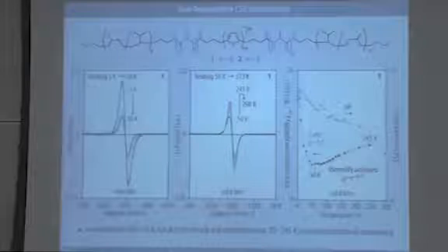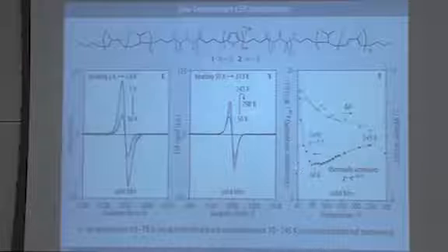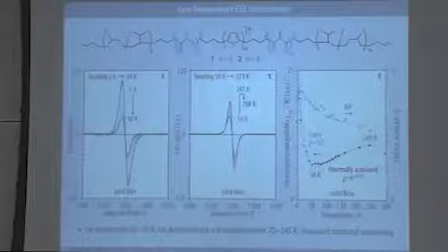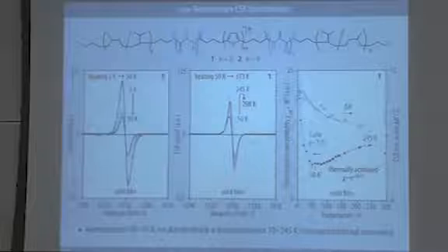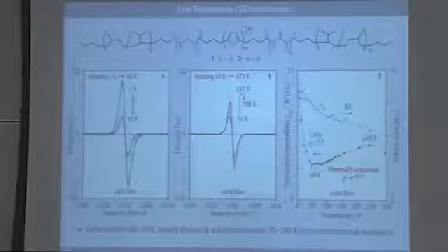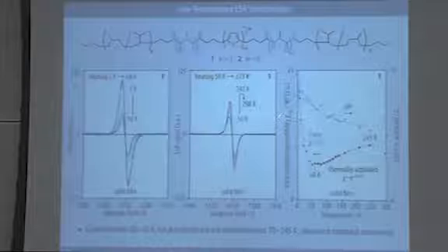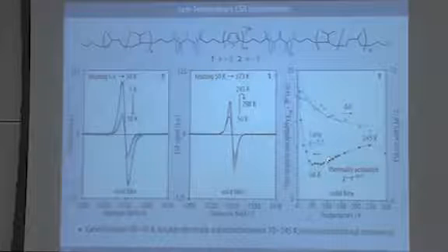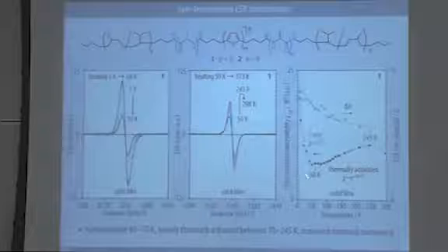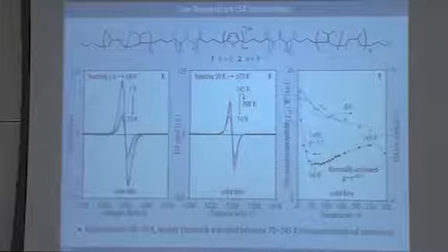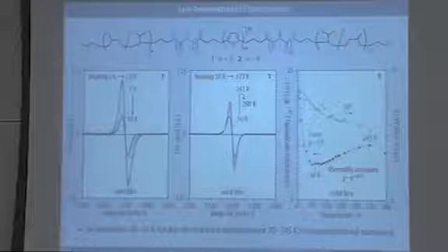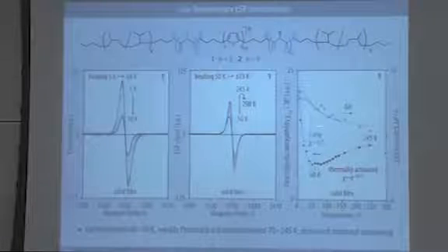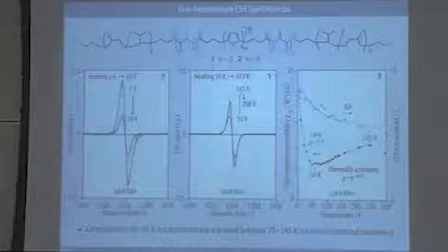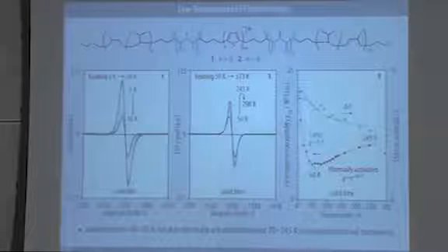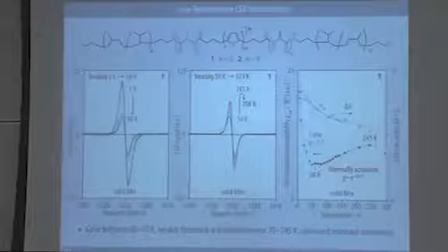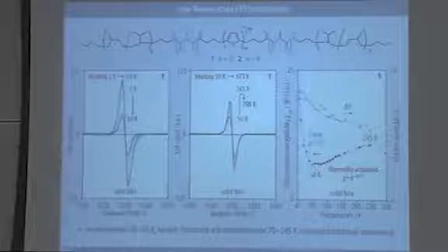and as you plot the doubly integrated ESR line as a function of temperature, which is a measure for the ESR accessible paramagnetic susceptibility of the system, you obtain a plot that looks like this. So in a low temperature regime up to 60 Kelvin, we observe a 1/T relation, which can be attributed to Curie behavior of localized spin carriers. So in this low temperature regime, this means that we're actually dealing with localized radical cations the way an organic chemist would draw them.